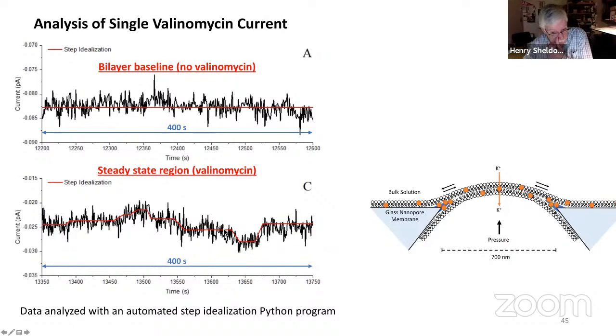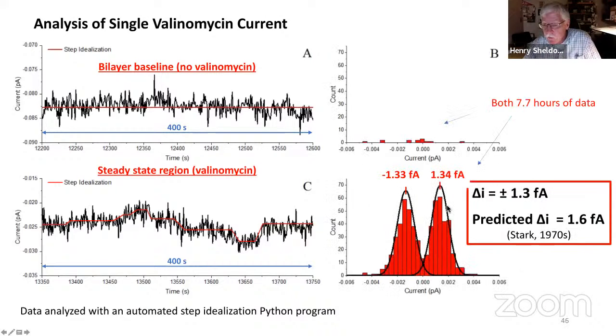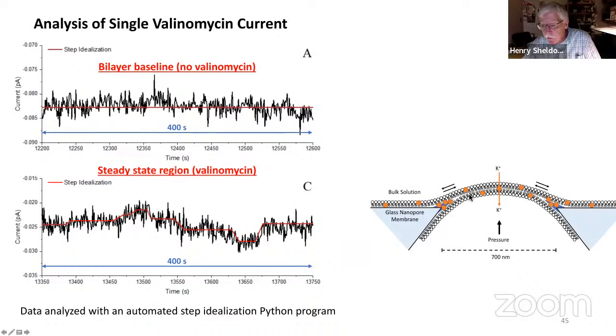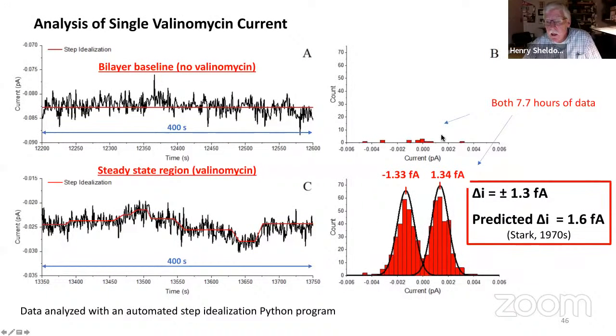We think this step structure represents the valinomycin moving from this torus region where you have decane, and it's very soluble in the decane, up into the bilayer film. So the model is the valinomycin's moving from the active region into this torus region and back and forth, and there's a steady state or an equilibrium partitioning between the bilayer and the decane phase. But anyway, if you take the data and you look at the distribution of these steps, this is what it looks like. This is for the baseline trace. This is what it is when you have the valinomycin in the film. Both of these distributions represent nearly 8 hours worth of data. All right, and it's a one-to-one comparison using the same analysis techniques, the same solution, the same bilayer, same experiment.